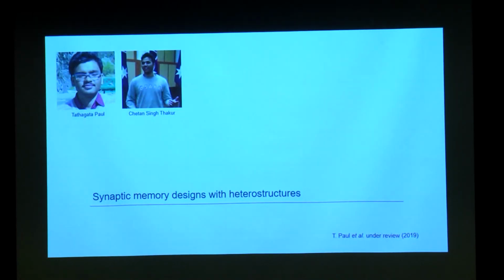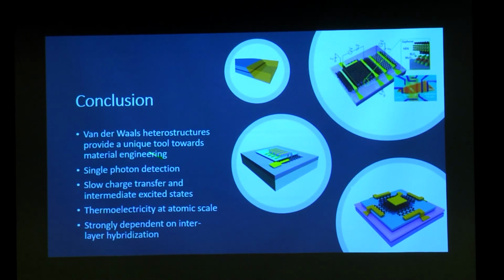What we have shown is that the van der Waals heterostructures can be used as an exciton source, and look at possibilities of looking at superfluidity in exciton condensates at high temperature, in the order of hundreds of Kelvin. We have asked the question whether a graphene TMDC heterostructure can host such excitons, and the answer to that question is probably yes. And apart from that, there are new possibilities of charge transfer that can lead to very unique lattice orientation dependent thermoelectric phenomena in these kinds of hybrids.